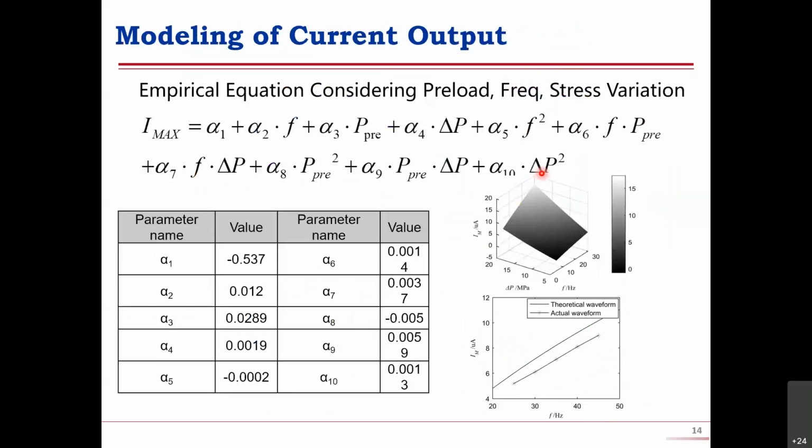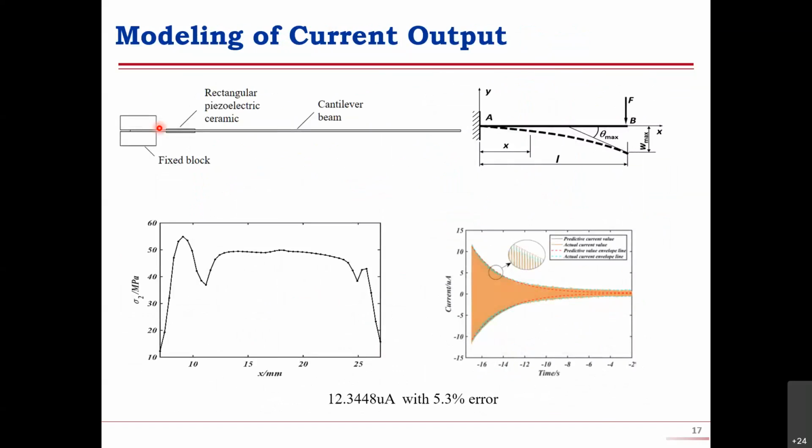How about on a cantilever beam? We can use finite element analysis to simulate or calculate the stress distribution on each part of this piezoceramic, and we consider each part as a current source.